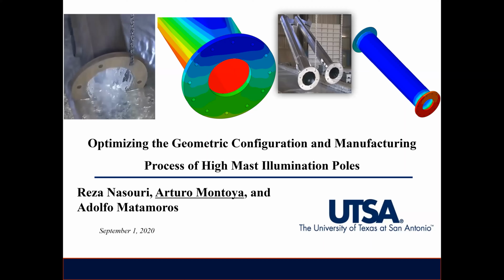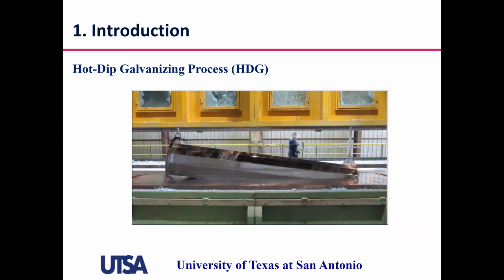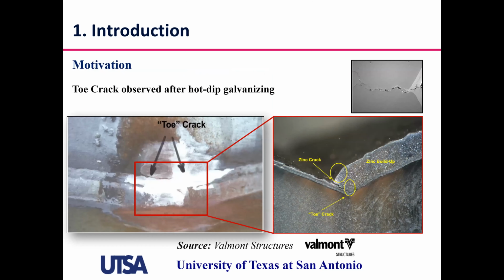So the motivation for our work is that most steel structures have to go through a galvanizing process because that creates a coating layer that protects the structures from corrosion. And it is actually a very effective method to protect steel structures from corrosion. However, it has some flaws because it has been detected that after this galvanizing process, they have detected small weld-toe cracks. And these weld-toe cracks developed during galvanizing.